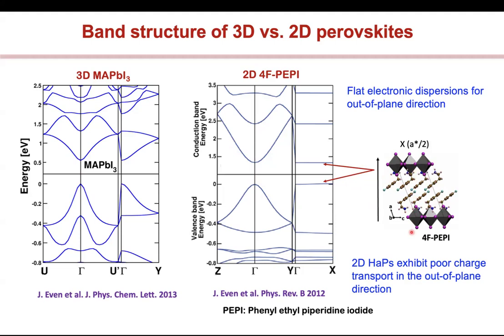But now if I go in this direction, if I do the same dispersion, which is this gamma to X, in this direction, then you see that I have an organic molecule here, and this organic molecule is insulating, which means that instead of getting these nice curvatures, I have these flat bands here. If I place a charge here and try to apply an electric field, this is not going to go anywhere. In fact, I'm going to have terrible charge transport in this direction. And that's indeed the case: if I try to move carriers in this direction, then you have really bad charge transport. Okay. So those are the differences.